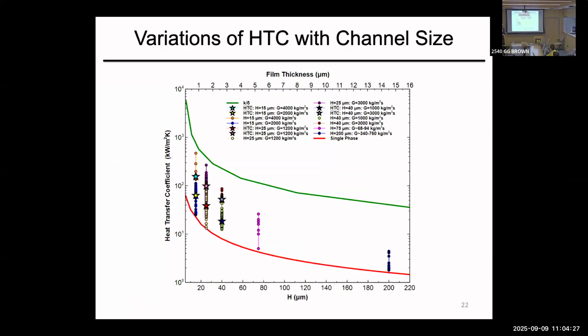What we found was so fascinating: we took all those different channels that we tested at different conditions, got the average, and put it on a heat transfer coefficient versus film thickness plot. This is an order of magnitude more than what is reported. All our data stays above the single phase, and below the hypothetical heat transfer coefficient for this thickness. Boiling is complicated, but once you understand the different elements, frequency comes into play. If I am able to sustain that thickness over the surface constantly, I can get extraordinary heat transfer coefficients. This is essentially proof for this case. And even with tight structures, if the fluid distribution is right, you can definitely get a high heat transfer coefficient.